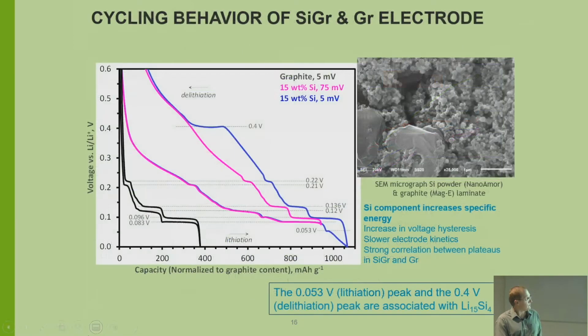Okay, now I'm just going to switch quickly to the negative electrode. Generally, it's graphite material, and most of the research is now trying to incorporate some silicon in the negative electrode. So here's a graphite particle. It's kind of a flaky material, you know, because it's like graphite grease. Those graphene sheets can peel off. And then you're also seeing silicon particles. So here's the voltage profile for graphite. As you're lithiating it, it has these different plateaus, different staging as you're putting lithium into those little honeycomb niches. And you get about 350 milliamp hours per gram. Now silicon, pure silicon, you can get about 3,000 to 4,000 milliamp hours per gram in it.